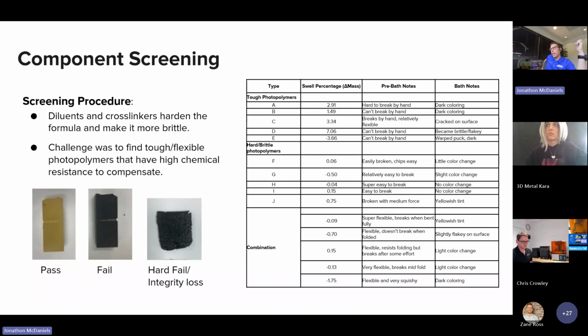Additions to the formulation that aid in printability will harden the material and make it more brittle. So you have to have these things to make it 3D printable, but they negatively impact the performance of the material. So the challenge was to find tough and flexible replacements to compensate for these necessary additions while also maintaining the chemical resistance. You can see some examples here of a good part, a bad test result, and a catastrophic test result where it just completely disintegrated in the electroplating bath.